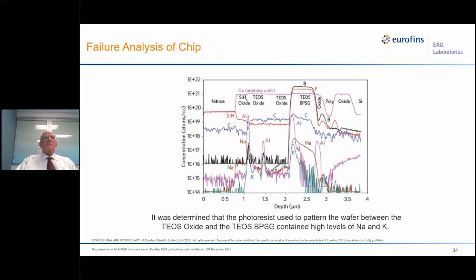But here's an analysis that we can do with charge compensation. It's a failure analysis of a chip. It's from a 100 micron area on a chip that had the plastic of the package removed in fuming acid, whatever it is that they use. The wires were still connected to the bond pads of the device. So we really didn't have to do anything more than just take the plastic off. And we see we have a nitride here. We have an SiO2 layer here.